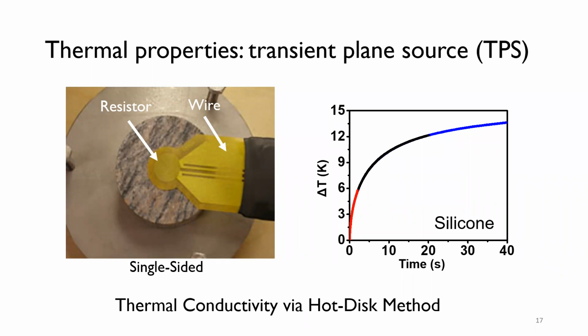So the plot on the right is what we're most interested in. It's a change in temperature as a function of time. So not just what is the temperature, but the change in temperature. Because then if you take a slope of this line, you can solve the thermodynamic heat equation to extract out what is the thermal conductivity. So we use an analytical method to do this, but we could measure it from the slope. And the difference between the red and the black and the blue lines is to show the reproducibility. You could get a similar thermal conductivity value from measuring 2 seconds or 20 seconds or 40 seconds. We get very similar values, and the measurement from one device to another is similar. The line's thickness is thicker than the error bar's size.